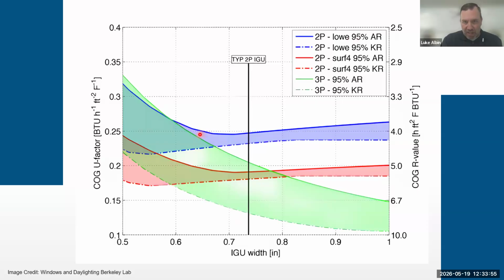As you look, we've got a solid blue line and then a dotted blue line. The solid lines here, and actually all the colors, are an argon gas fill, and the dotted lines are a krypton fill. So the blue lines represent a single low-E coating. The red lines represent a dual low-E coating. And the green lines are triple pane low-E coated, again with argon and krypton.